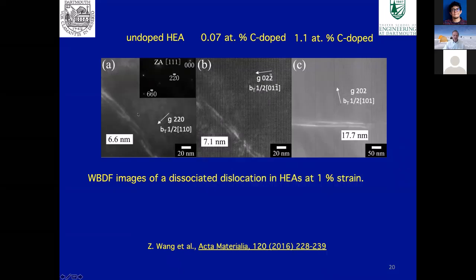So we looked at the partial separations in this material. These are Shockley partials here, looked at using weak beam imaging. This is the undoped high-entropy alloy. This is with 0.07 atomic % carbon. This is 1.1 atomic % carbon. And you can see that the partial separations increase, so the stacking fault energy is going down.